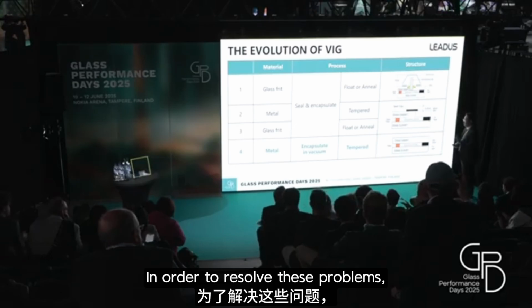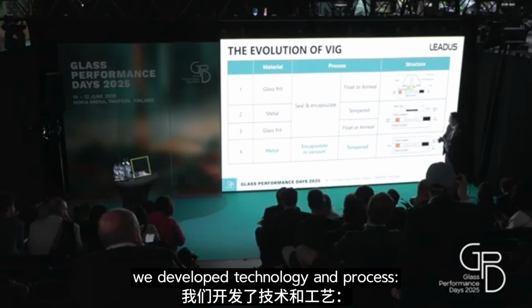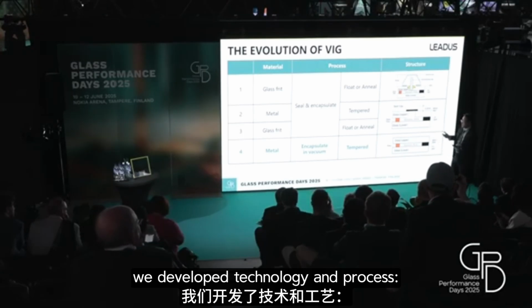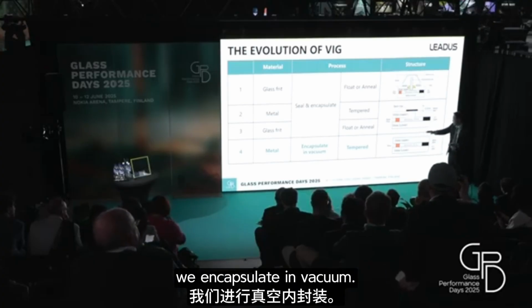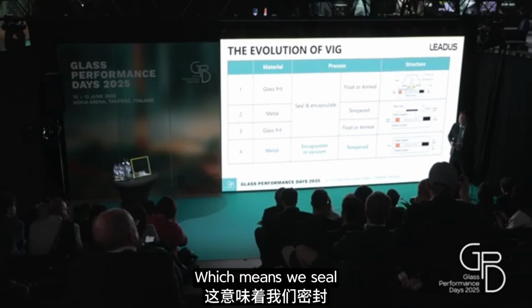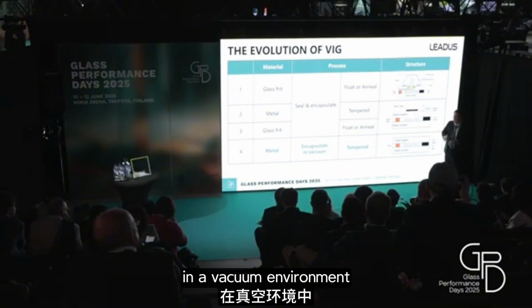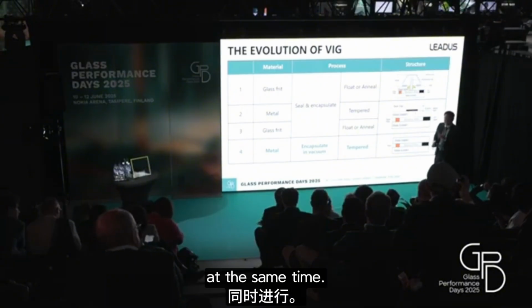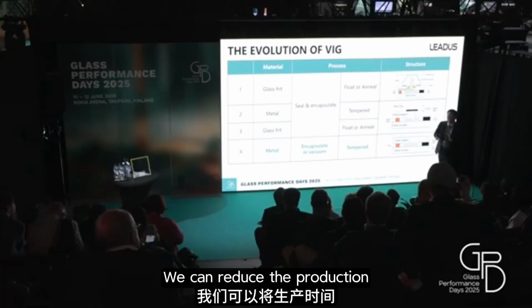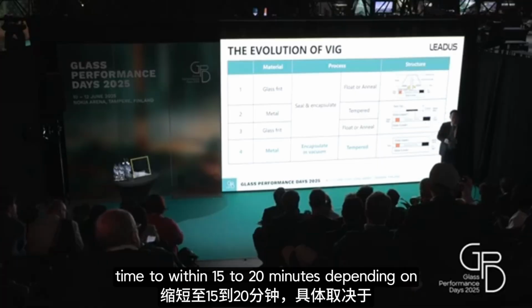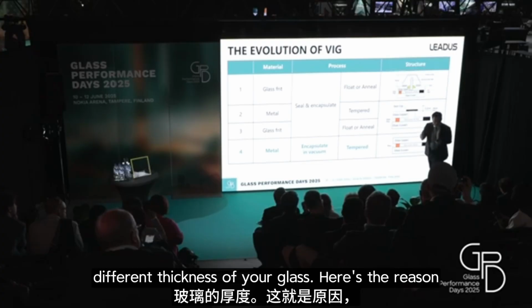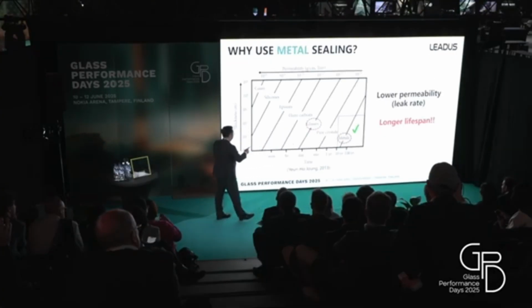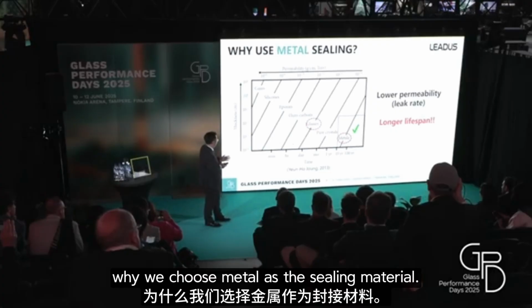In order to resolve these problems, we developed a technology and process where we encapsulate in vacuum, which means we seal in a vacuum environment at the same time. We can reduce the production time to within 15 to 20 minutes, depending on the thickness of your glass. Here's the reason why we choose metal as a sealing material.